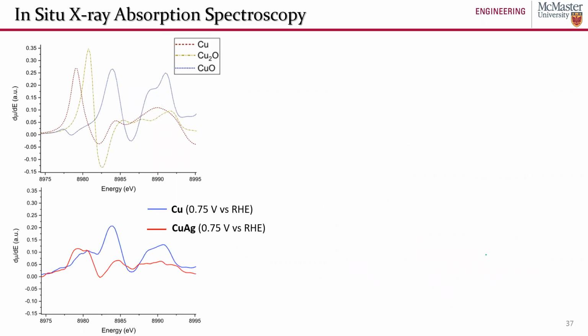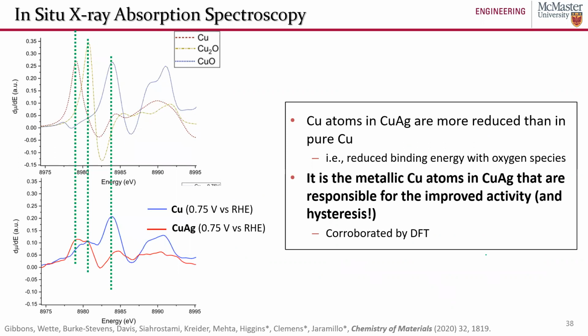I'm not going to dive into the weeds of this, but essentially what we found is that when we compared our copper silver catalyst to pure copper, the copper atoms in our copper silver thin films were in the metallic state, whereas when it was pure copper, they were in their oxidized state, and copper oxide was not able to do the oxygen reduction. So we identified that it was the metallic copper atoms in silver copper, where the presence of silver allowed those copper atoms to maintain their metallic state, that gave us that boost in activity. It also provided the hysteresis that we observed, because the hysteresis was caused by the oxidation and the reduction of those copper atoms. And we did a bunch of density functional theory. We collaborated with one of our colleagues to corroborate these understandings.